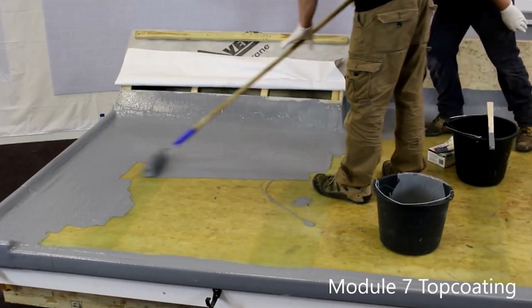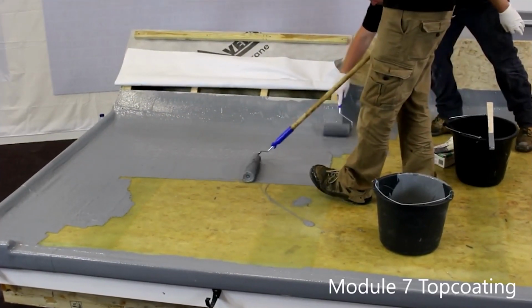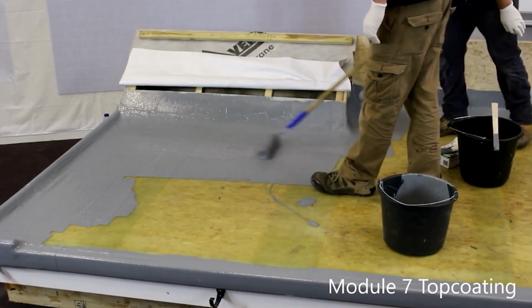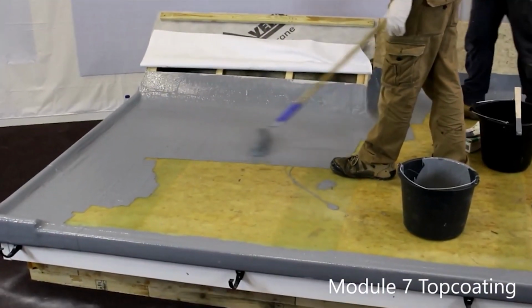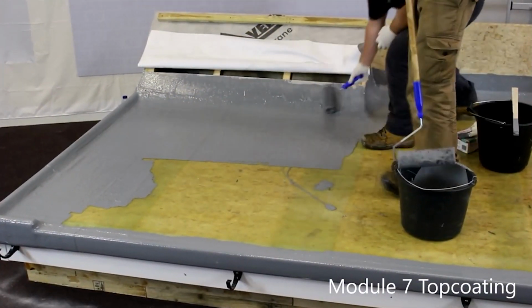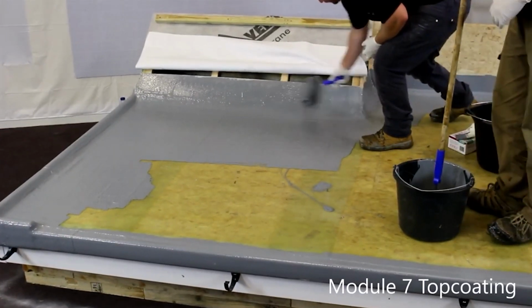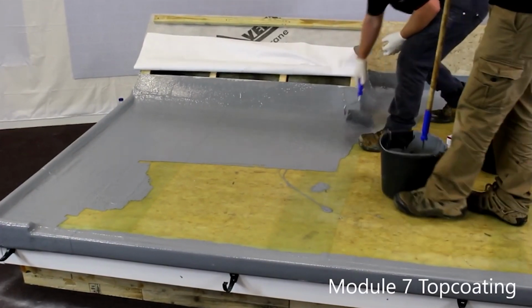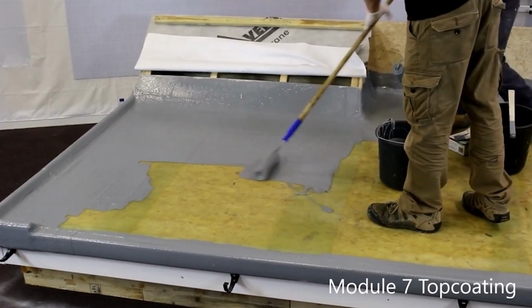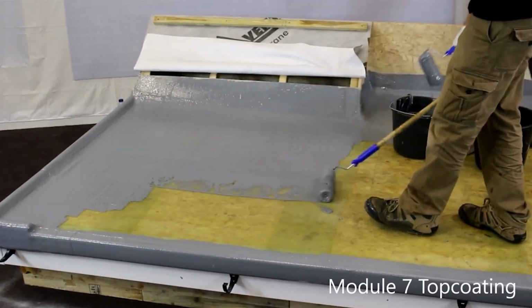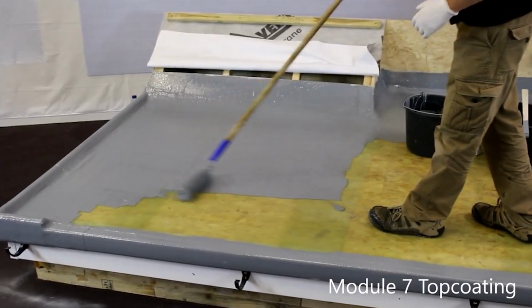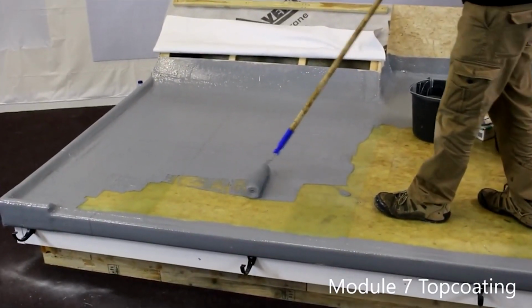Two common mistakes in fiberglass roofing are top coat too thin or top coat too thick. If the top coat is too thin, through erosion of wind and dust and dirt over the years, it will wear away and will shorten the lifespan of the roof. If the top coat is too thick, with contraction and expansion, you start to get cracks in the top coat.